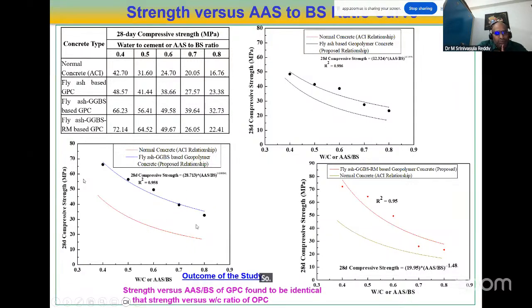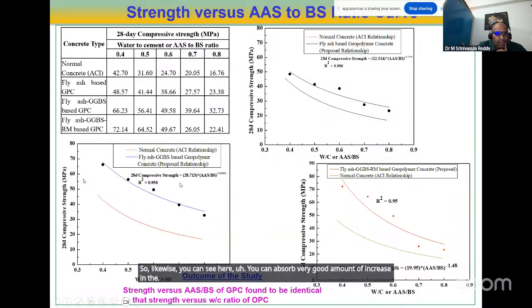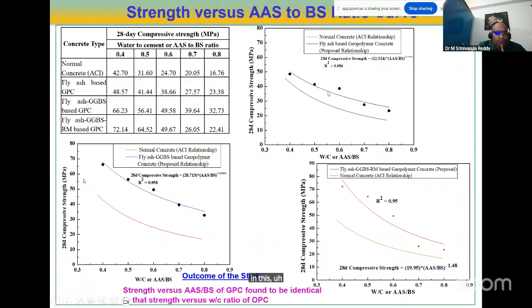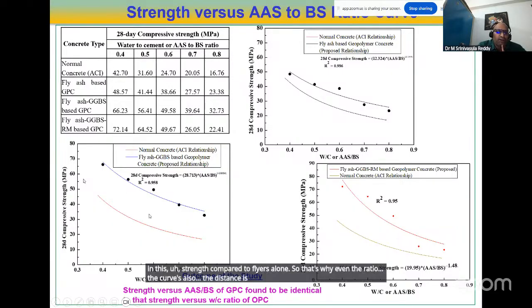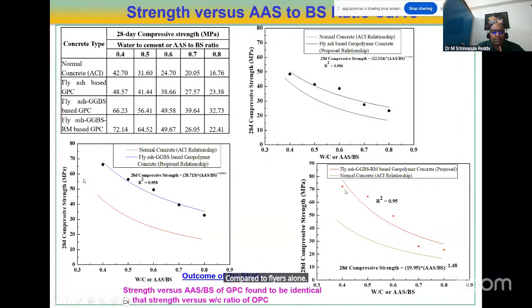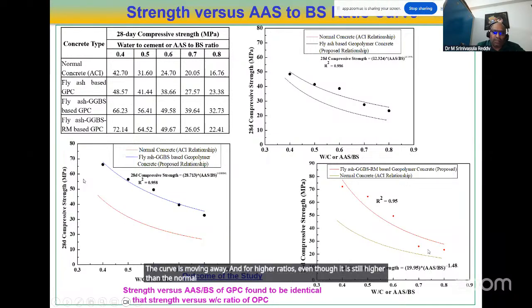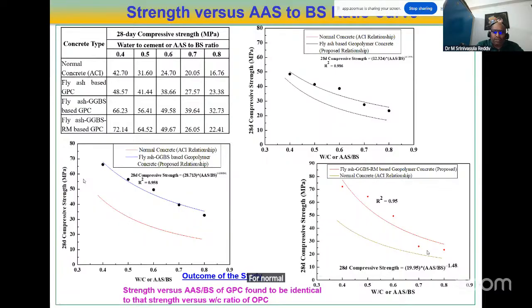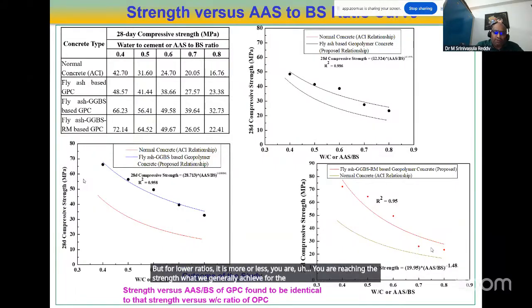Likewise, you can observe a very good increase in strength compared to fly ash alone. That's why the distance between the curves is far compared to fly ash alone. At the lower ratios the curve is moving away, and for higher ratios it is still higher than what we generally get for normal concrete. But for lower ratios, we are more or less reaching the strength we generally achieve for normal concrete at similar ratios.